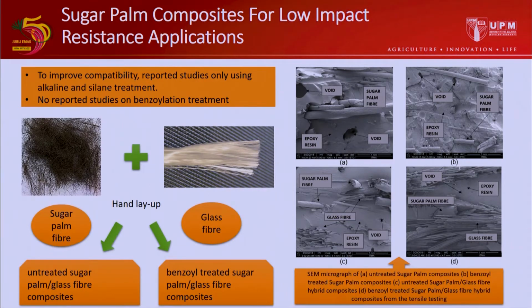The next study, entitled "Sugar Palm Composites for Low Impact Resistant Application," was successfully conducted by Dr. Shafiqa Nur Azri Safri. The figure shows the SEM micrograph of 4 different composites, which are the untreated sugar palm composite, benzoyl-treated sugar palm composites, untreated sugar palm glass hybrid composites, and treated sugar palm glass hybrid composites. The SEM shows that with benzoylation treatment, the sugar palm fiber becomes rougher and improves the adhesion of the glass fiber to the matrix.